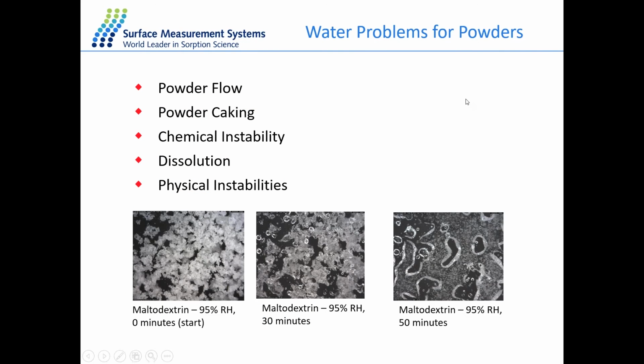Moisture is everywhere in the real world, and the relative humidity can vary in different areas. The interaction of moisture with solid material has a great impact over a wide range of industries. Especially in the food industry, moisture causes lots of different problems. For example, powder caking affects the powder flowability, as well as the instability of the material, both physically and chemically. Moisture can also induce phase change for some food materials, for example, the dissolution or deliquescence of sugar at higher humidity range. So it is very important to study moisture sorption behavior for the prediction of shelf life or the stability of food products. And DVS can be a very useful tool here to study this kind of moisture sorption behavior.